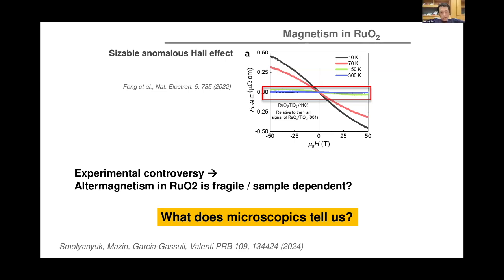How do they know that? That's a very good question. But I think Libor, you are here, right? You are one of the co-authors of this work. So Libor, tell us. So first of all, these are potentially doped thin films. Yeah, we will come to the doping. And the assumption was that the z-axis is along the c-axis. So when you put it there, you do not expect any anomalous Hall effect. But when you put it into a magnetic field, there is luckily in the rutile structure a Dzyaloshinskii-Moriya interaction, which couples the Néel vector to the magnetic field. In a magnetic field, it starts to rotate.